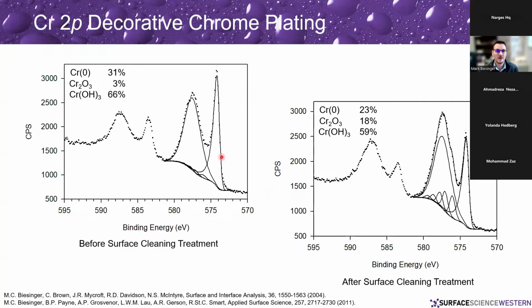So we have here a decorative chrome plating where, before surface cleaning treatment, we had so much metal underneath with mostly chromium hydroxide on the surface. And after surface cleaning, we still saw a similar amount of oxide and hydroxide, but it was now more oxide present along with chromium hydroxide. So it's a more structured, less hydrated surface.